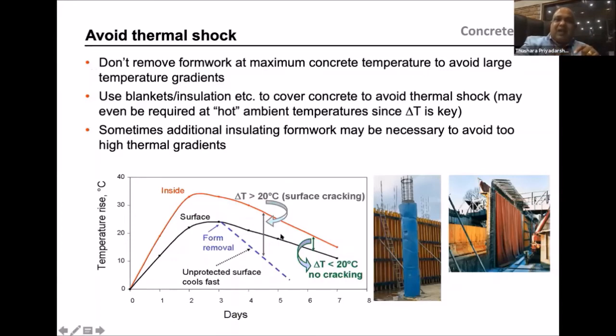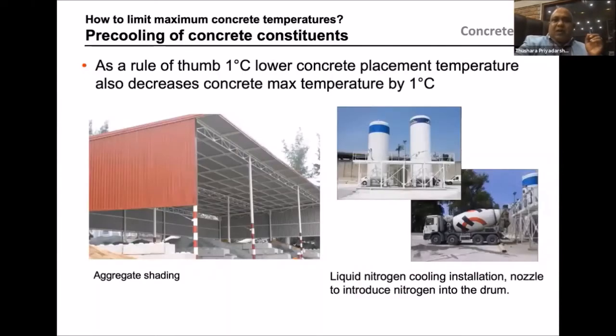If the temperature gradient is high, there will be some surface cracks. If the overall temperature goes higher, there will be some long-term durability issues, which can be very costly for us to repair. So how you can cool down the material is quite easy. The best way to reduce the temperature of any concrete is to shade your aggregate. Nitrogen cooling is not available in Sri Lanka as far as I know, so it can be used, but it will be very costly.